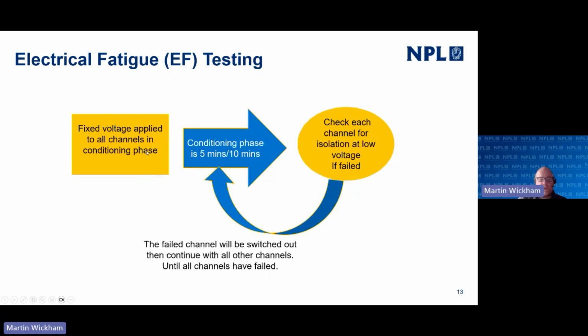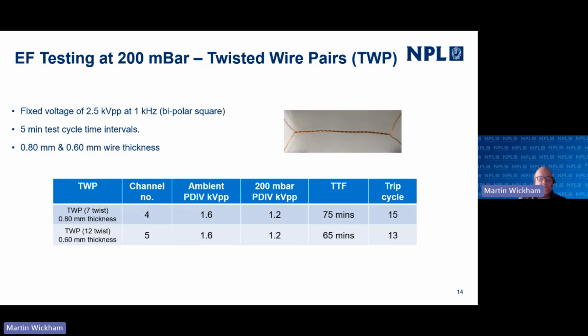We apply a fixed voltage to all the channels for a period of what we call the conditioning phase. So we apply that voltage across those 6 samples simultaneously for generally 5 minutes. Some of this data is for a 10-minute conditioning phase. And then at the end of 10 minutes, 5 minutes mostly, we will check that each channel is still isolated, and we'll do that at a low voltage. If it's failed, we will switch out that channel and just continue to condition the remaining channels that are still in the system. So we run this system until all 6 channels have failed normally.